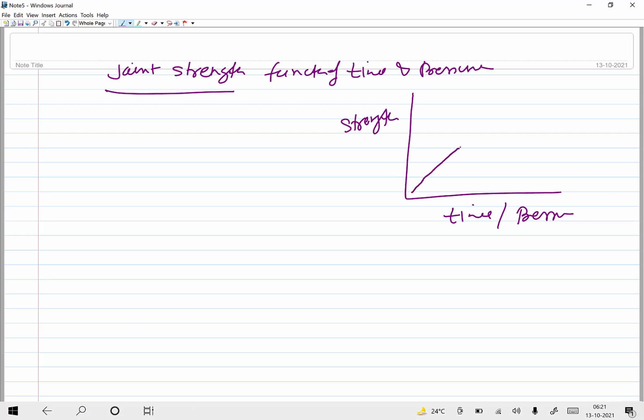So initially with the diffusion bonding time, the joint strength increases, and then it gets stabilized. This is the stage when we find that the metallurgical joint has been completed. In the initial stage, with the increase of these two parameters, the voids at the interface are reduced, and when these voids are completely eliminated, the curve gets flattened and there will not be any further increase in the joint strength with the increase of the diffusion bonding time and the bonding pressure.